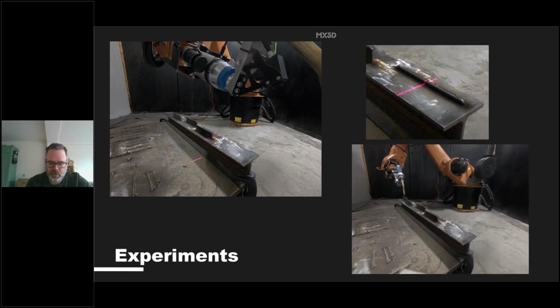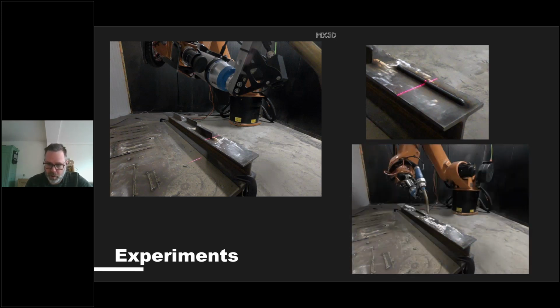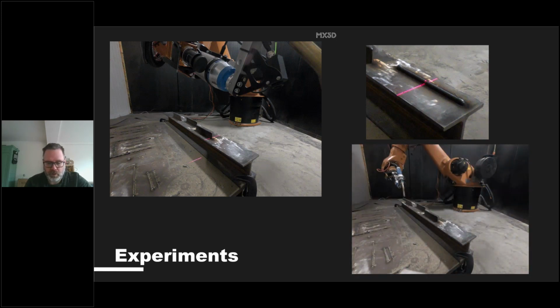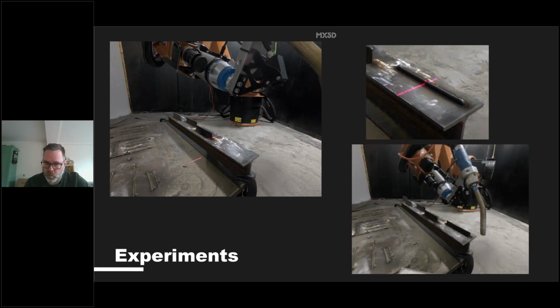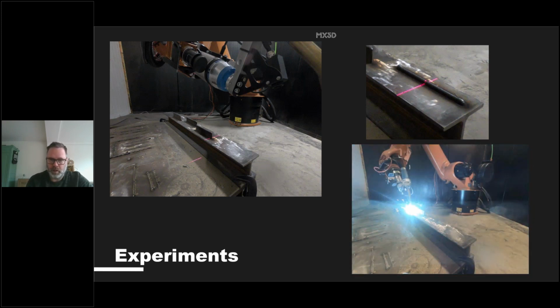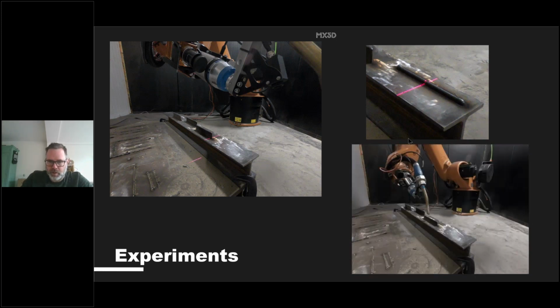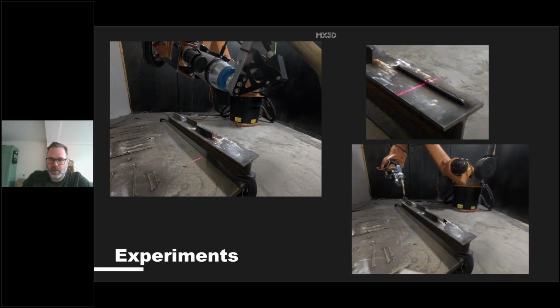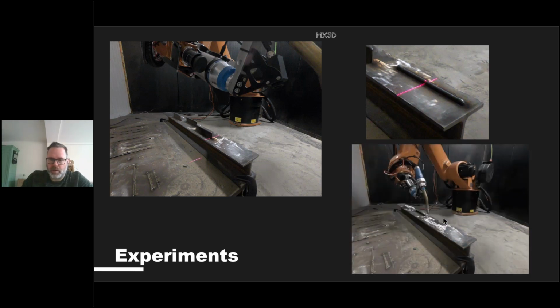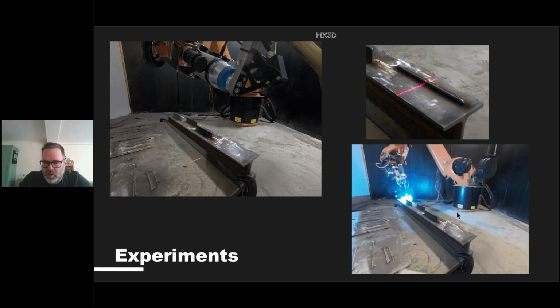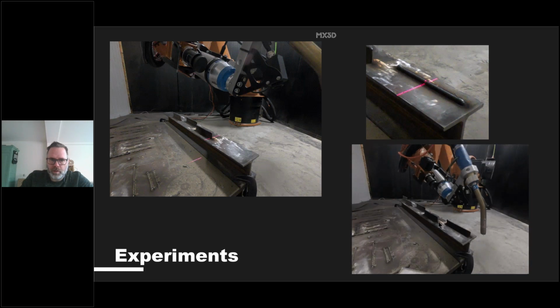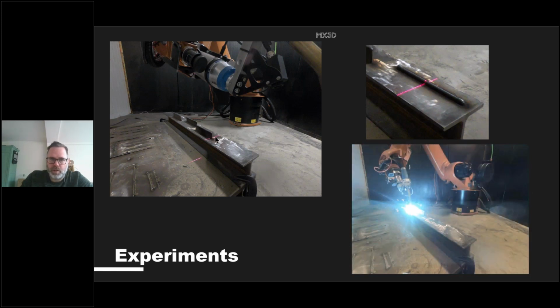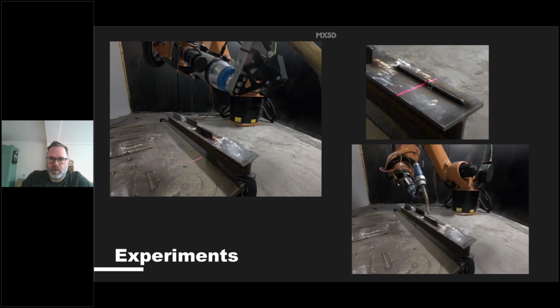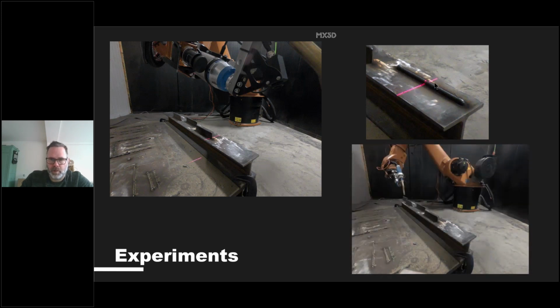It starts with a scan of the substrate, then the robot prints the first layer of the first wall, and then it's scanned again. The results are saved, and the toolpath of the next layer is calculated automatically, and the next layer is printed. You can see a time lapse of that on the right side, and you can see we try to minimize the warping of the substrate, so we alternate the position on the beam. On the left side, you can see the robot doing a scan, zoomed in on the upper right side. You can see a projection of the laser blade scanning the wall.